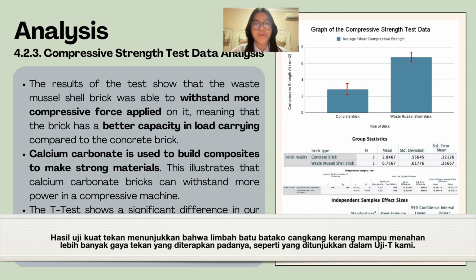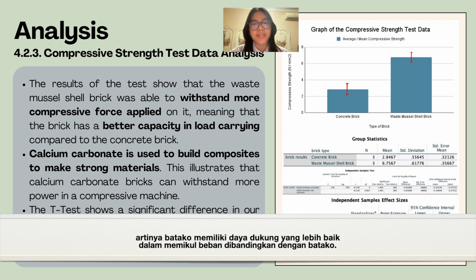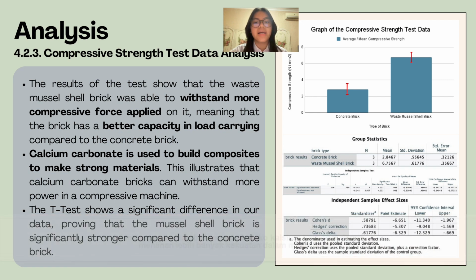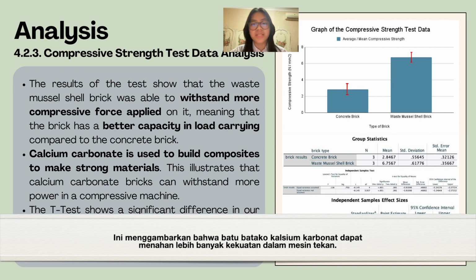The results of the compressive strength test shows that the waste mussel shell brick was able to withstand more compressive force applied on it as shown in our t-test. This means that the brick has a better capacity in load carrying compared to the concrete brick. This is due to calcium carbonate being used to build composites to make strong materials. This illustrates that calcium carbonate bricks can withstand more power in a compressive machine.